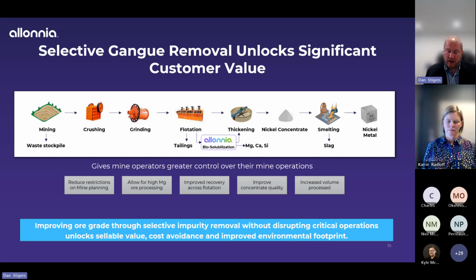Where we are seeing the value of the technologies that we mentioned earlier is that by treating only a side stream of material, we can effectively remove a significant portion of magnesium, which is known to have all these deleterious issues when it comes to nickel smelting, at the flotation step. We can then take that beneficiated material out of our process and send it back to the rest of the process, so that the overall grade of the concentrate going into thickening is of higher grade and much lower magnesium.